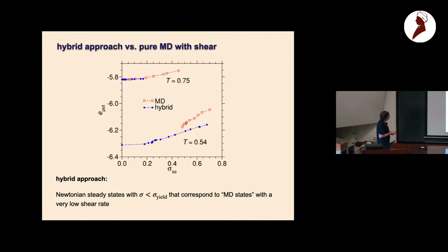Now, this is also the case at the low temperature, but here we can expect—this is the potential energy at zero stress, so with no shear—that with these states we are close to the steady state. So via this hybrid approach, we can generate states at very low shear rates, at least below the shear rates where we would still have a nonlinear response.